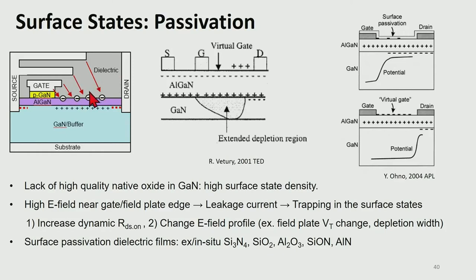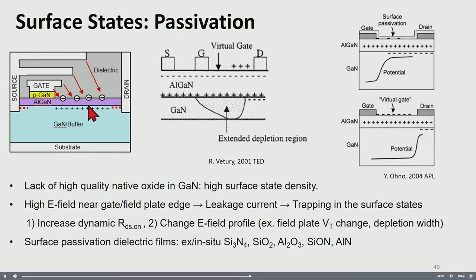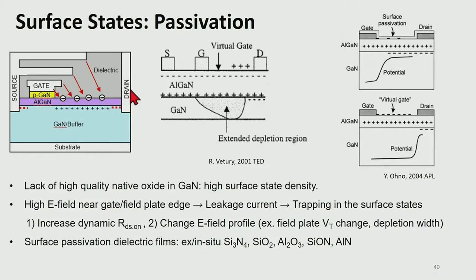And gallium nitride does not have a high quality native oxide, which can passivate these surface states like silicon oxide for silicon. So once many electrons are trapped in these surface states, these electrons can deplete the 2DEG channel and increase the device resistance. And also, in the off state, these trapped electrons can increase the depletion region and push out the depletion region. And since this is similar to having an additional gate in this access region, it's also called the virtual gate effect.